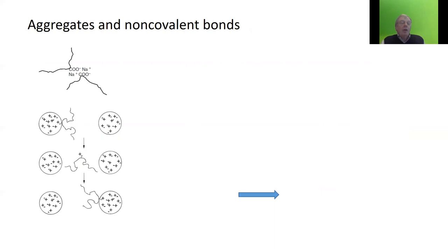Here I have the example of an ionomer. In this ionomer, we have a hydrophobic polyethylene chain, and we have carboxylic acid groups introduced as methacrylic acid comonomers. And these form, after neutralization, strong dipoles which aggregate, and they form clusters, ionic clusters inside the material. So that's a thermoreversible cross-linked material. If you heat it up, the clusters get more mobile and you can transform it in shape. You can reshape it. It can flow.